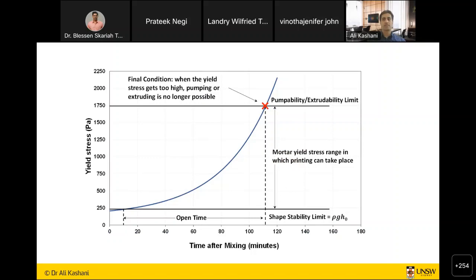And we look at the yield stress development of the material versus time. We need a good initial yield stress to make sure the material has a good shape and stability, so it doesn't flow after extrusion. And we also have an upper limit, because if the material gets too stiff, it's not going to be extrudable or pumpable.